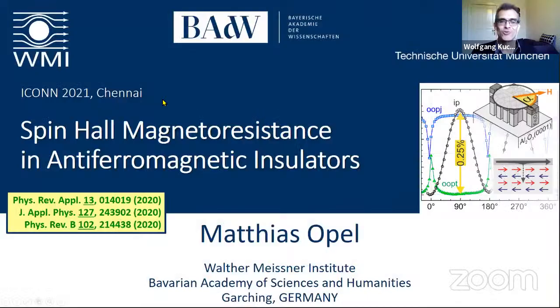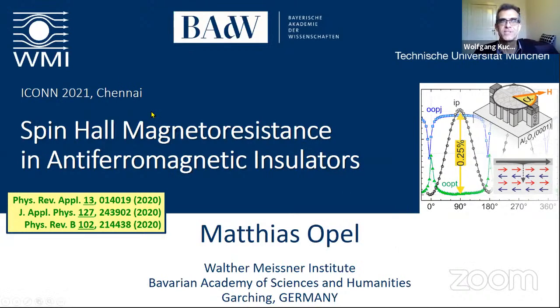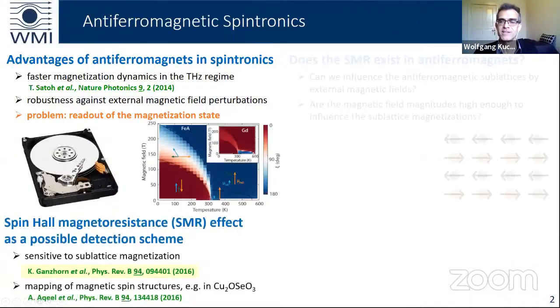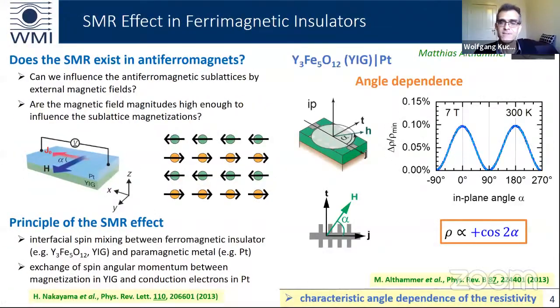Yes, hello. So you mentioned shortly in the end the nickel oxide that had this behavior with the field. Is this also explained by the domain structure, so that the increasing field made the larger amplitude, because nickel oxide has this more complicated domains with the T domains and S domains and so on? This is what you meant by the field dependence?